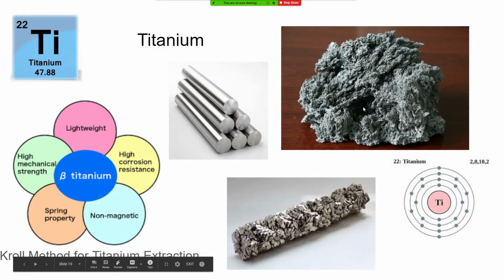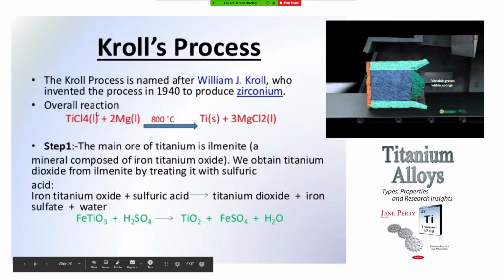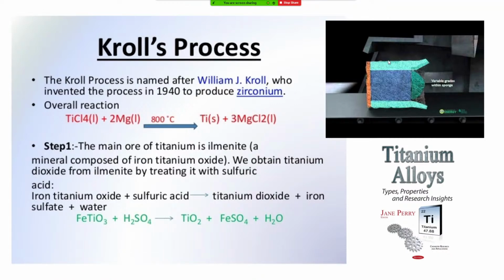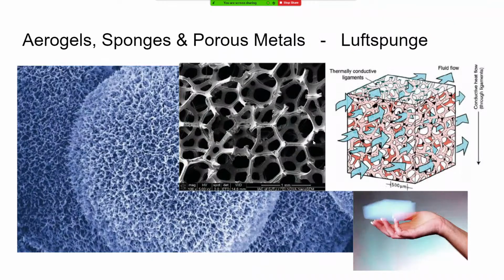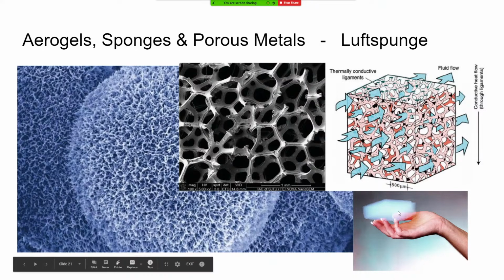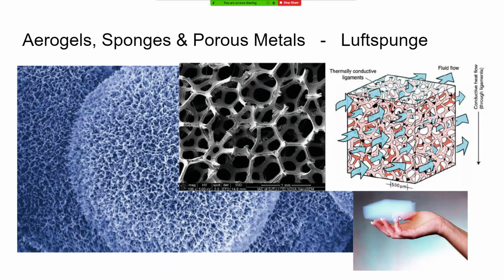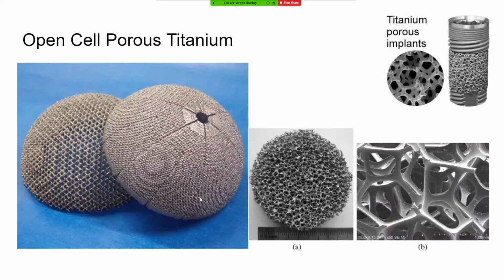Titanium, there's a Kroll method for purifying it that they use to make this kind of sponge of different purities, and they take off the different pieces. But sponges are an interesting thing because it turns out a lot of different metals can be used to make sponges, and also other things like aerogel, which is a silica sponge. It's like silica gel, but the gel's been replaced with air to make aerogel. And these kinds of aerogels and aerosponges, including open cell and porous titanium,